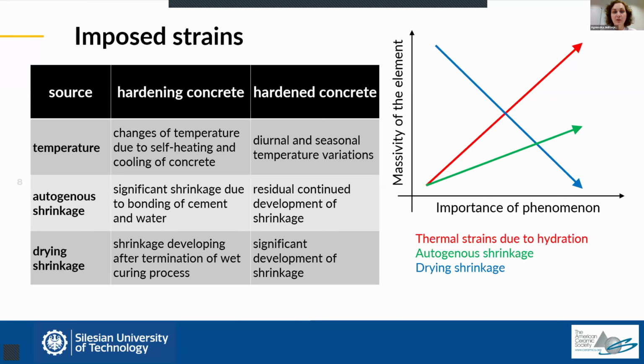because we say that drying shrinkage is mostly a superficial or surface related effect. If we have a massive element, the drying shrinkage effects will mostly appear on the surface, but will not influence the volume of the element that much. We also need to remember that all of these processes not only occur in early ages, but also during the whole service life.